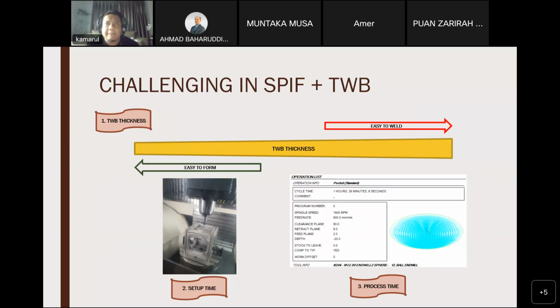So when the specimen is thin, 1 mm or less, the possibility of failure and warpage is very high. Whereas if the sheet is thin, 1 mm or less, it's easy to form. But if the specimen is quite thick, maybe 2 mm and above, it's very easy to weld. Then there is no warpage at all if we use 2 mm material thickness. But it's very difficult to form.